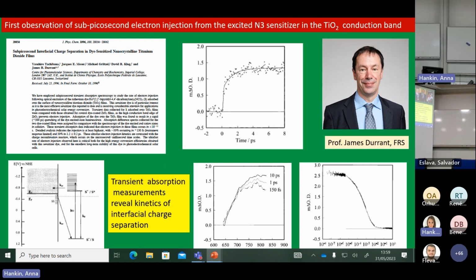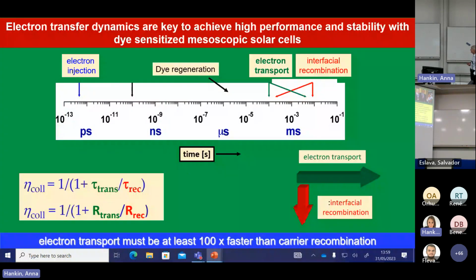And what that tells you is that the dye, it's a very simple calculation, shows you can take the dye over these many, many turnovers that you have together when you have dye in the sun for 20 years. It's about 100 million. And so that was a key feature, kinetic feature, which was then followed up by measurements on transport and recombination.